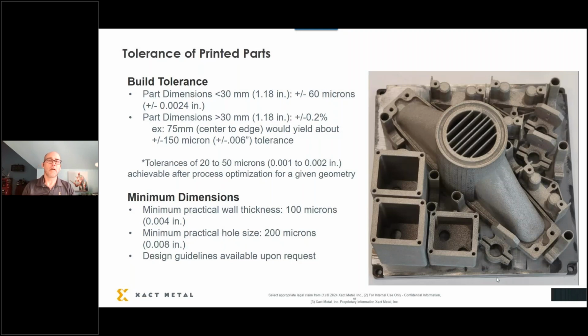Minimum wall stock, you can see down here, we can do stuff at 100 microns thick, or about 4 thou thick. Not that you're going to be molding over walls that are 4 thou thick, but just the idea that for printing parts itself, you can get some very fine detail with it. Minimal practical hole size, 200 microns, about 8 thou. I actually have a little sample that we put in our booth with a 4 thou hole going through it, and you actually have to hold up the light in order to see through it. So we can get some very fine detail with this technology.